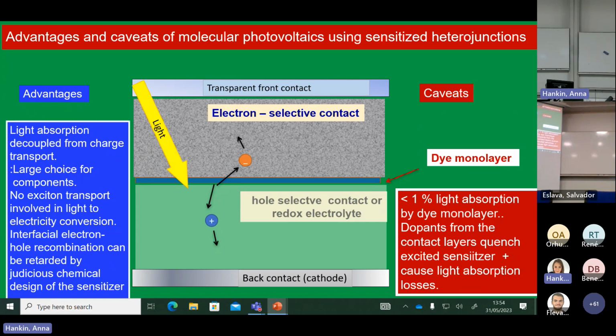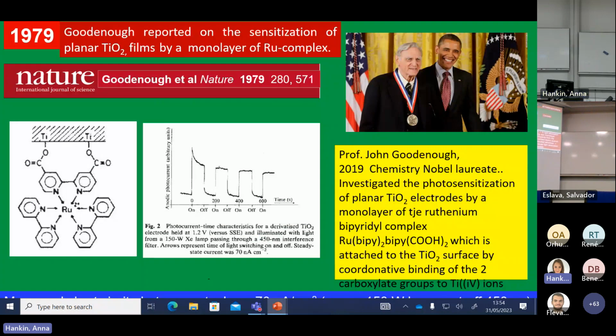And one of the main caveats is that you don't get the light absorbed in a monolayer. Also, if you use a compact layer as a selective charge extraction layer, then you will have to dope it. Otherwise, it's not conducting the charge. So the dopants very often interfere with light absorption and quench the excited state.